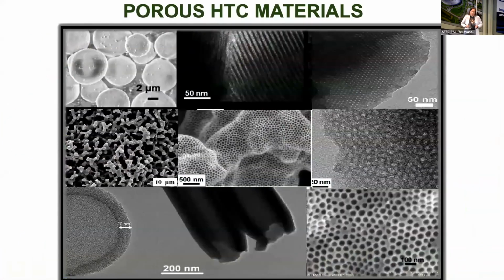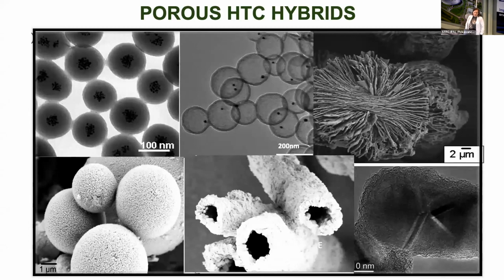Just to give you a flavor, these are some of the morphologies that we can make with these carbon materials. We can take a biomass precursor and turn it into a tailor-made carbon for a particular application. I work a lot on batteries, where you don't want a high surface area, and we can do this. If you want catalysis, depending on the process, we can make nice conductive carbon supports in all shapes and forms. We can also hybridize this with other inorganic nanoparticles in a one-step process that, as I said, happens under more mild conditions from biomass derivatives.